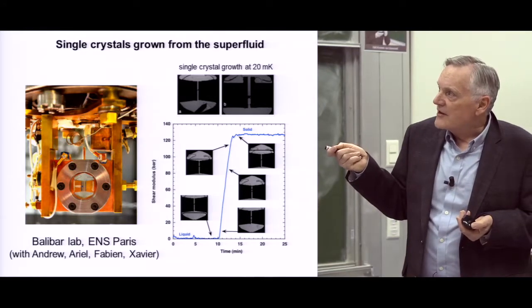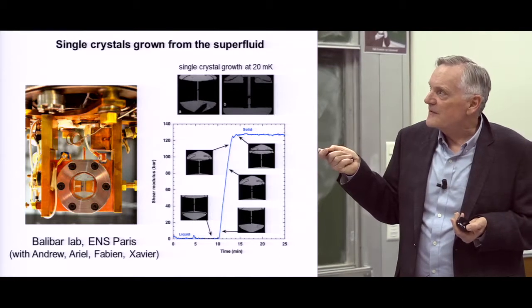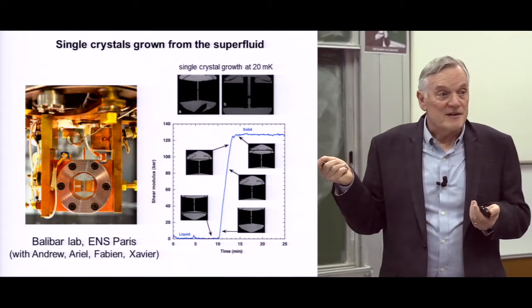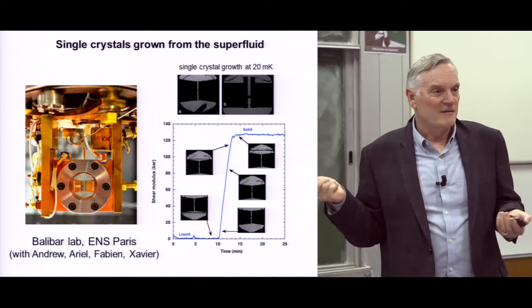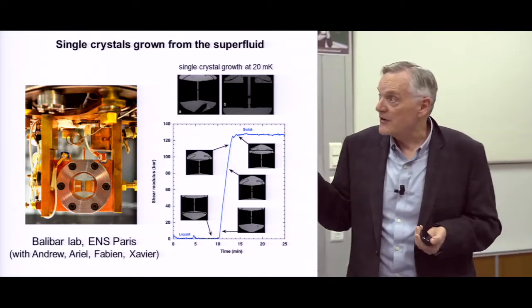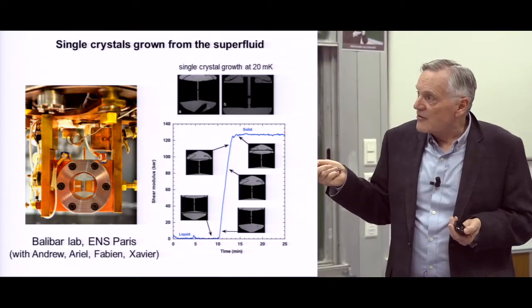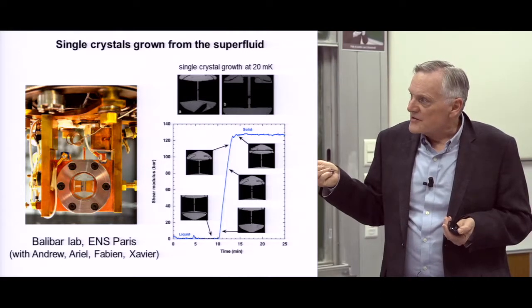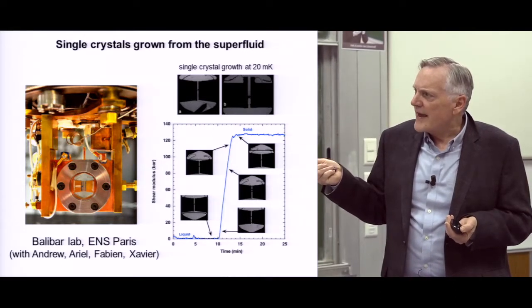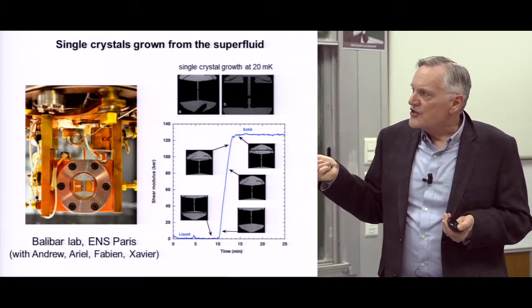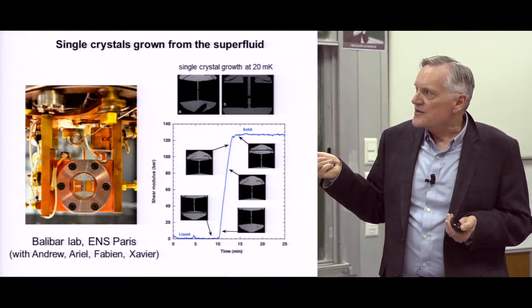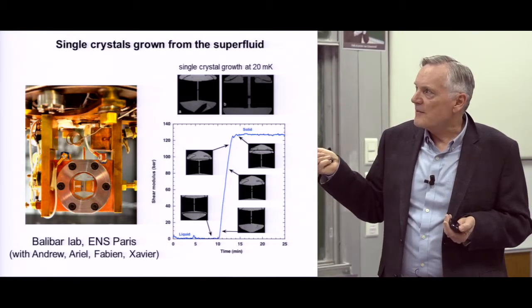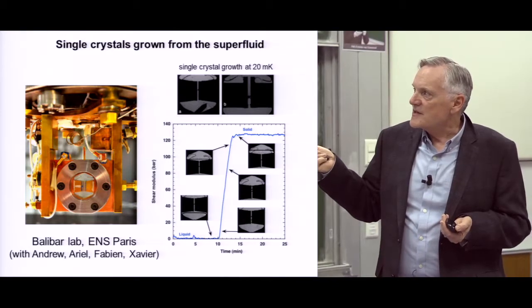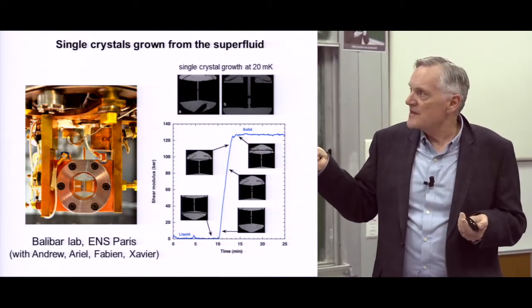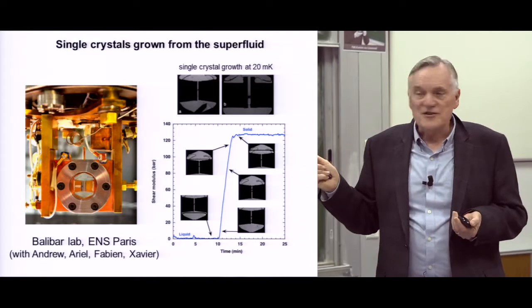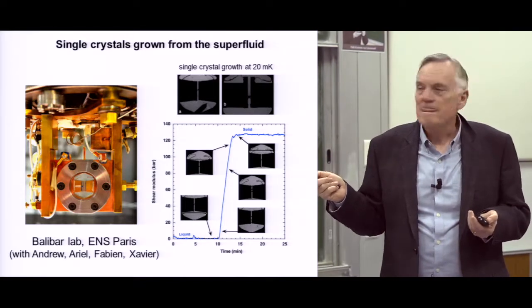Here you see one starting, if you can see it from that distance. It's a very nice hexagon. You can tell right away, you know, helium's a hexagonal crystal. You can also tell the orientation. And as it was grown, the crystal's at the bottom, and as it starts to grow up through the gap, this measured shear modulus goes up and up, and so it's halfway up, it's three quarters of the way up. And once it exits, the solid helium's above it, then it just stays the same. So this is the shear modulus. The difference is the shear modulus of the solid in the gap.